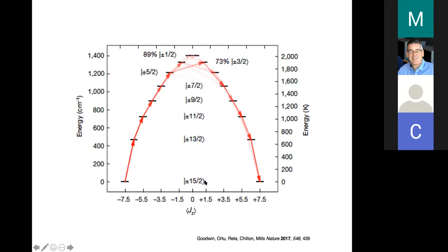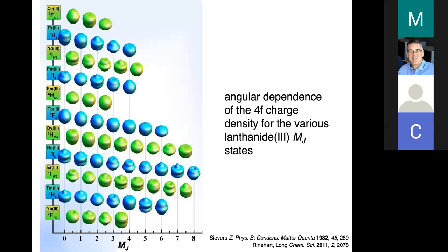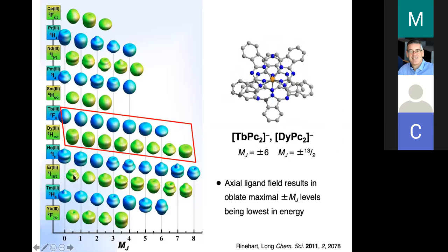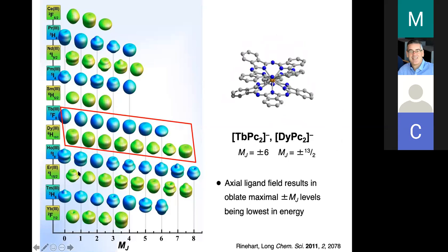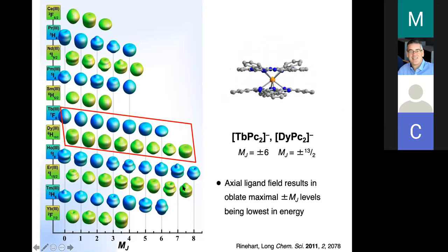And indeed, for that, if we go back and look at the shapes, this is a very good question. If we look at the shapes for erbium 3 plus, you can maybe understand this 1/2 best avoids those nitrogen ligands. That shape avoids it better than these others, and that's why it winds up at the bottom.